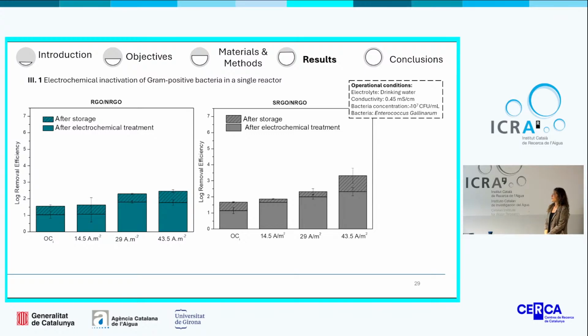The electrochemical inactivation of gram-positive bacteria in case of reduced graphene oxide and sulfur-reduced graphene oxide as an anode is compared in this graph. As was previously mentioned, we were also comparing the storing of the treated sample. According to the obtained result, during the open circuit conditions and in line with our previous study, we did not enhance the inactivation of bacteria, even functionalizing with sulfur. Then, in both cases, with the application and increase of current, we could observe an increase in the elimination of bacteria, which is slightly higher in case of sulfur-reduced graphene oxide, leading to 3.3 log removal, compared with 2.5 in case of reduced graphene oxide.